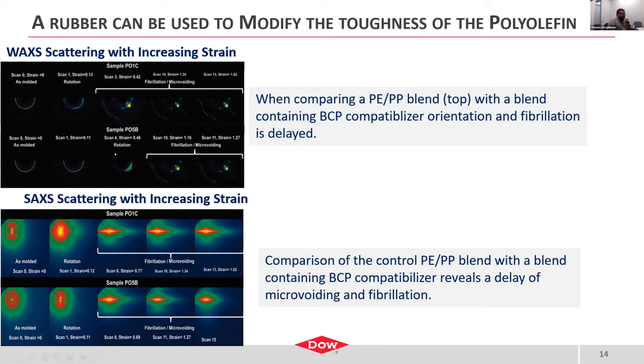However, when you add a compatibilizer to the material, you see a distinct delay in the lamellar rotation and microvoiding events in the material. It becomes much less of a fibrillar scattering pattern at higher strains when you have this compatibilizer in there. And a similar thing is observed in the small angle X-ray scattering as you go from a very isotropic material to anisotropic, to the fibrillation and microvoiding. When you add this block copolymer compatibilizer, it delays these failure mechanisms in the material. And what that does in turn is increase the toughness.